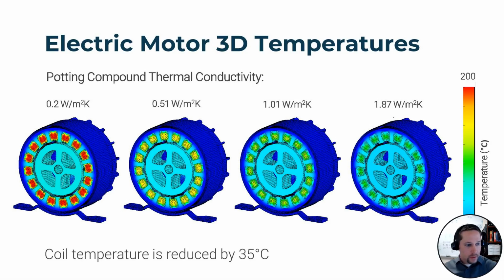These are results for different potting compound thermal conductivities. So they range anywhere from 0.2 watts per meter Kelvin to 1.87 watts per meter Kelvin. I think I've got the units a little wrong here. It says meters squared, but that's a meters Kelvin. And so we can see by increasing the thermal conductivity of the potting compound, we can reduce coil temperatures by about 35 degrees Celsius.